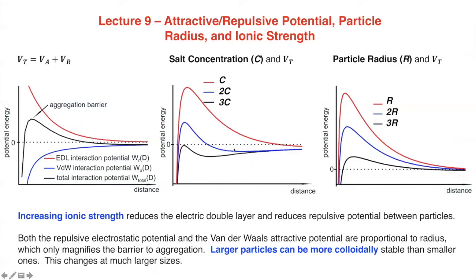And so a very common trick with an electrostatically stabilized colloid is to add salt to induce aggregation, where the particles suddenly all stick to one another and you get big aggregates that then settle out of solution. Okay, so adding salt helps separate electrostatically stabilized colloids from solution.